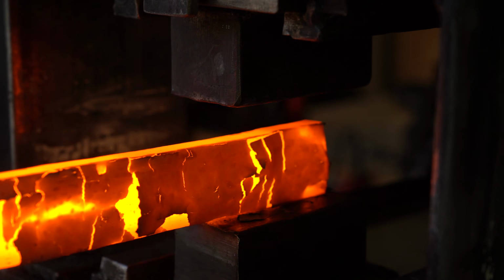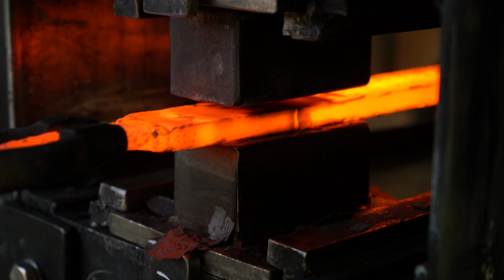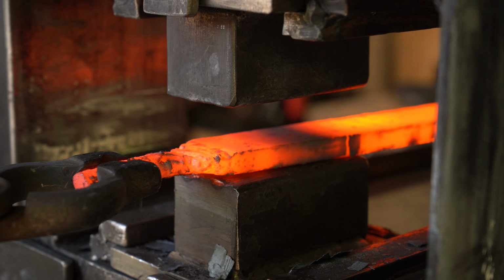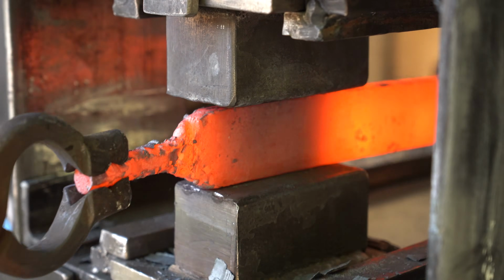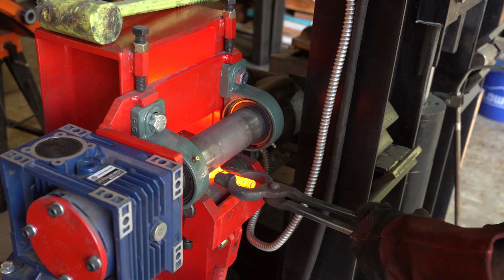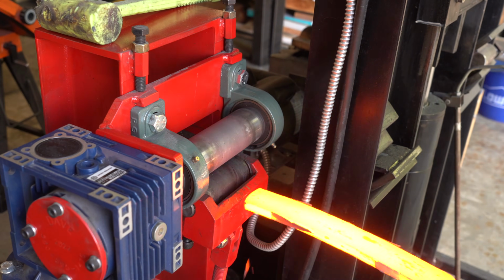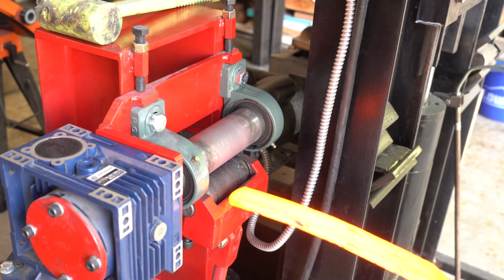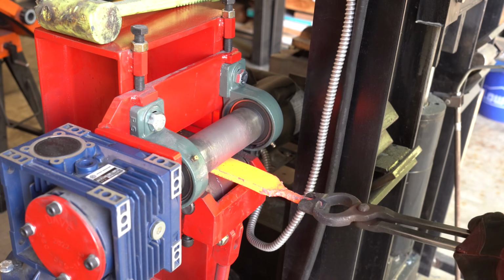One thing the hydraulic press is not good at is thin stock. It just sucks the heat out too much. So we're going to be switching to the rolling mill. The rolling mill only contacts the steel a little bit, so you get a lot of work done with each heat. You'll see here how quickly I stretch it out.